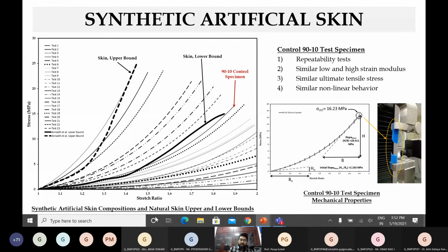So any of our material compositions which we have prepared, if it falls in between this upper and lower bound, we can call it a synthetic artificial skin variant. Okay, so that's the way of iteratively making sure that we have a composition which is unique and which falls within the skin upper and lower bound and can be called a synthetic artificial skin. Apart from that, once this step is done and we have narrowed down to, let's say, 6 to 7 compositions or range of compositions which can mimic the skin properly.